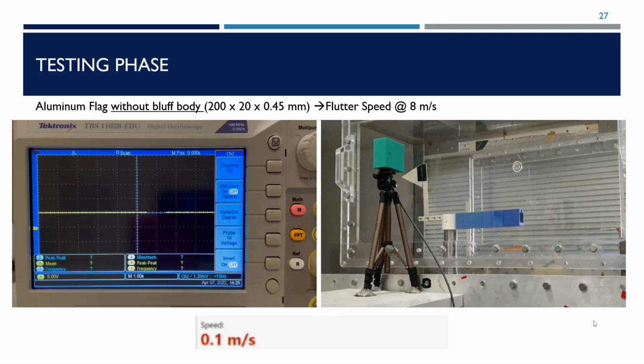Our third test also uses an aluminum flag without a bluff body. However, dimensions are now 200 millimeters in height, 20 millimeters in width, and 0.45 millimeters in thickness. From this test, we can conclude that the flutter velocity of this flag is 8 meters per second.